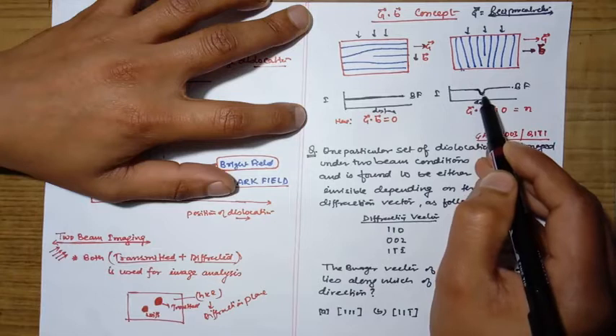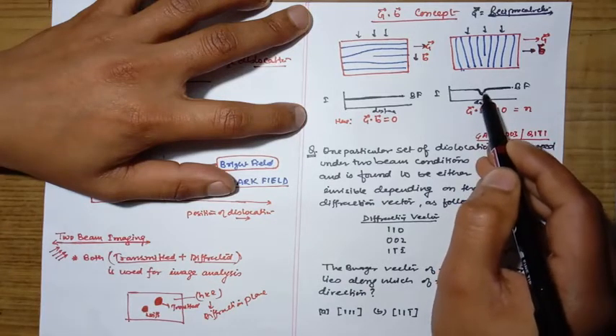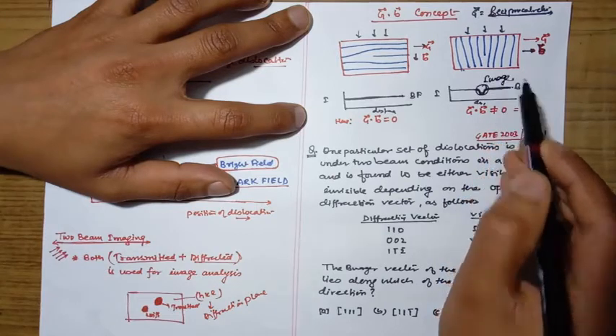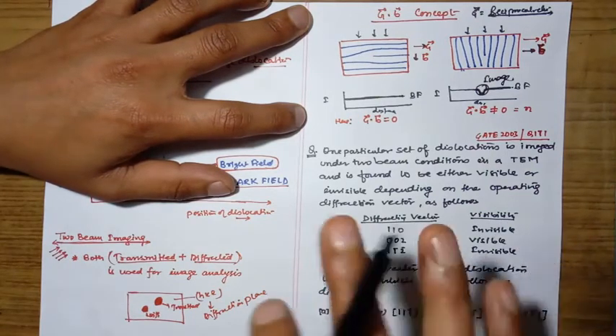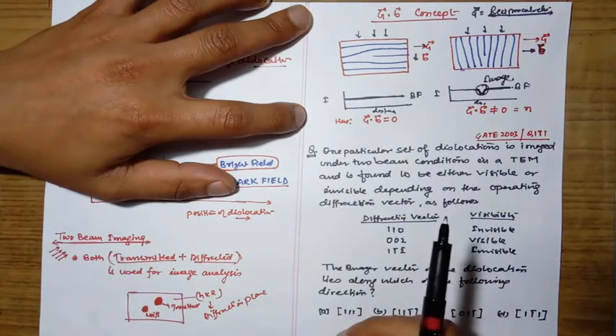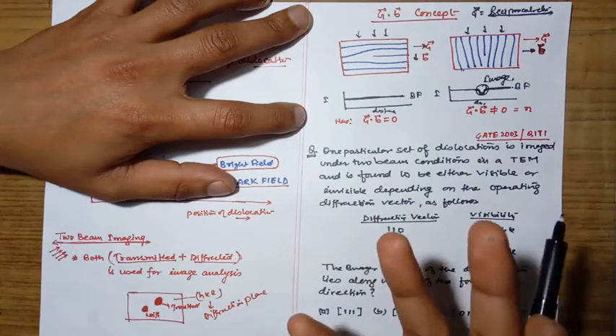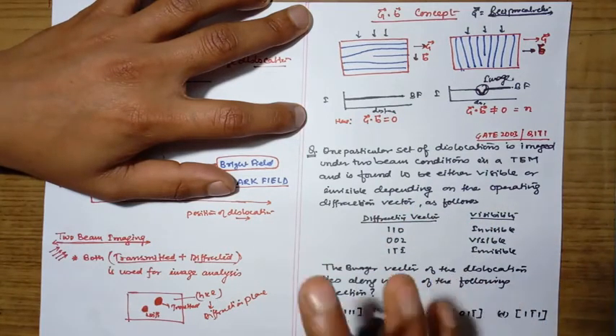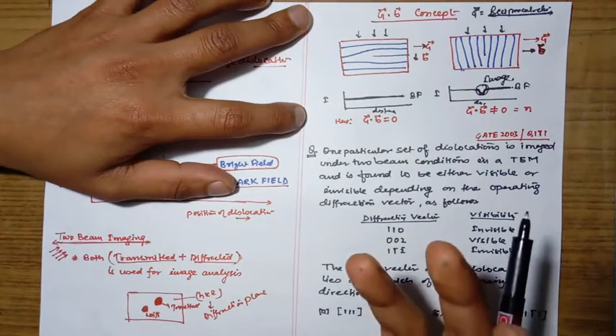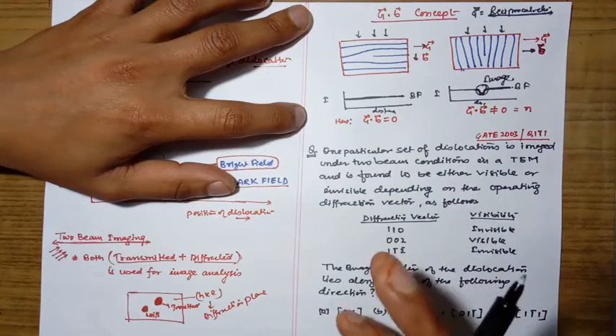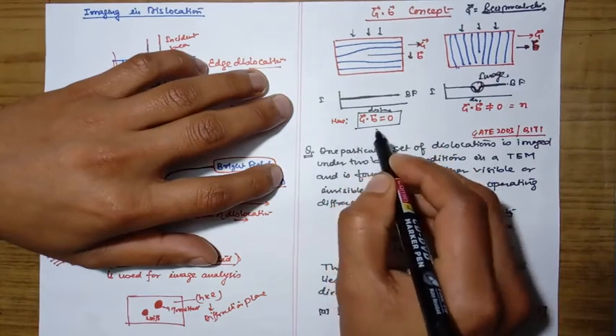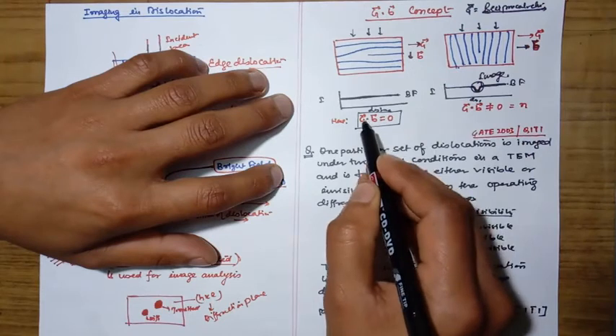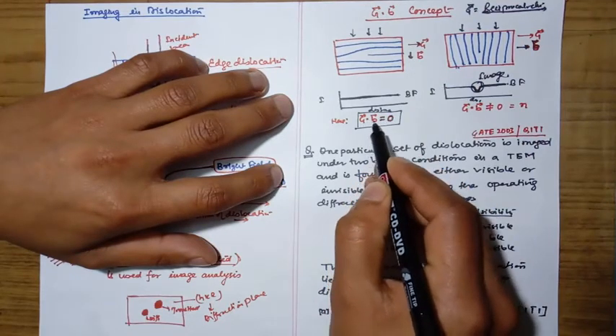We see things under a microscope through intensity differences — less intensity appears dark, more appears bright. Applying this: when G is perpendicular to B, G·B = 0, meaning no visibility — this is the condition of invisibility. When G·B is not equal to 0, the dislocation is visible.